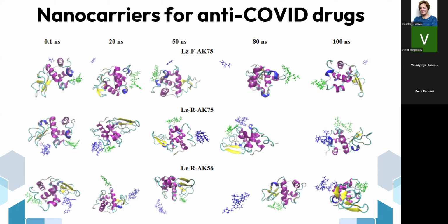To evaluate the principal possibility of such a combination and to check the stability of such complexes, we conducted a series of molecular dynamics simulations, based on top-scored docked protein complexes, and the molecular dynamics results have been analyzed in terms of different parameters such as backbone root mean square deviation, radius of gyration, etc. For some systems, we observed that the detachment of either the drug or the fluorescent dye molecule occurs, and this means that such complexes cannot be recommended for further development, but some systems appear to be very stable and very effective.